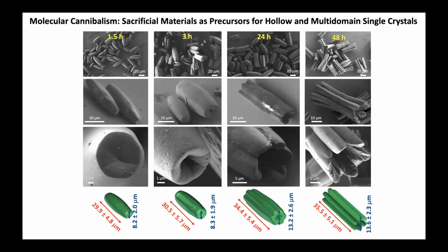We followed the formation of these systems. Here are some time-dependent electron microscope studies. So we stop the reactions after given time periods. And you see, doesn't matter if it's 1 hour and a half, 1 day, 2 days, it's a uniform system of beautiful crystals. But at the short reaction times, the crystals seem to be solid.